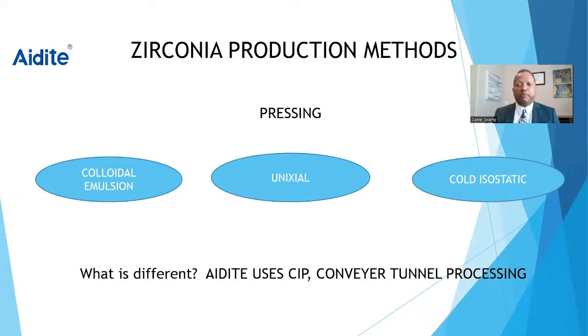So the cold CIP production, we also have a conveyor tunnel processing for pre-preparations, or I should say pre-sintering of the zirconia. Every zirconia that's made has to go through a pre-sintering process where the additives are actually burnt out, so you have a very pure zirconia. So we feel that using the conveyor tunnel processing method, every grain of zirconia is already baked and cured. Okay, you can see the microstructure of this material is very dense, 100 microns. So the denseness of this material lends to a very high strength.